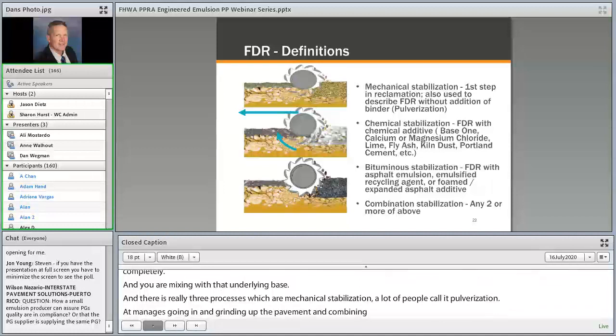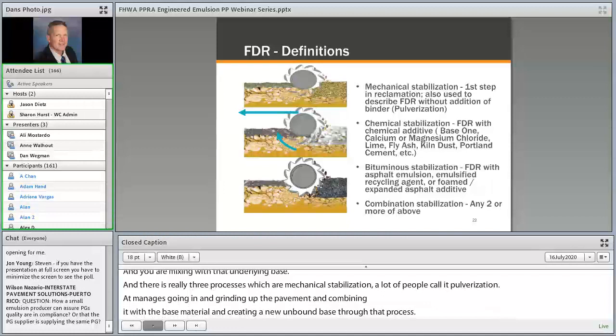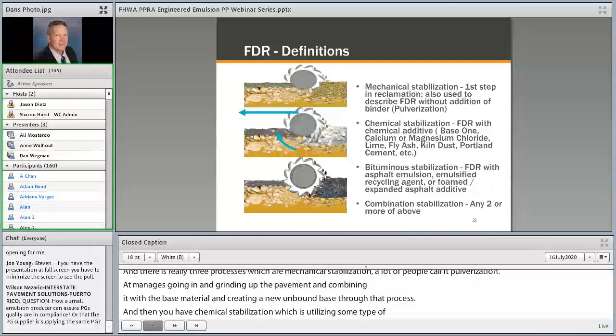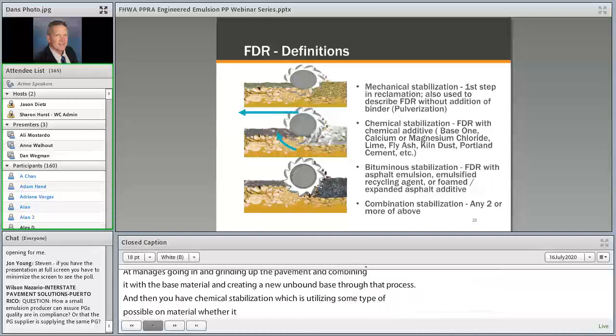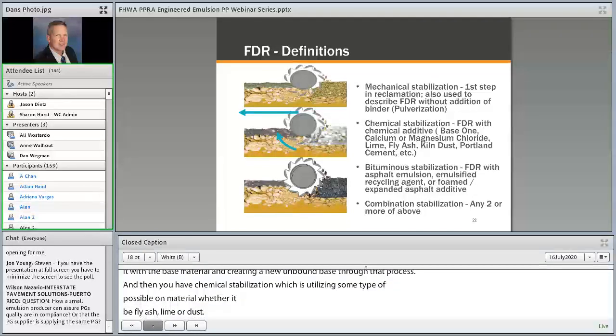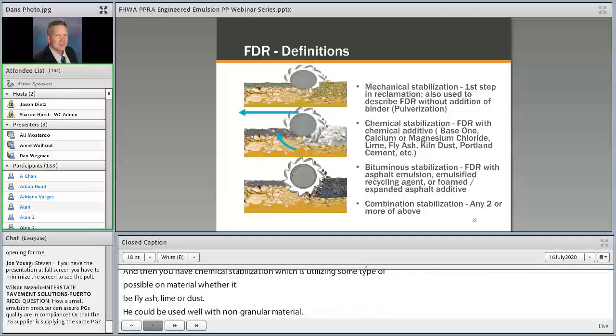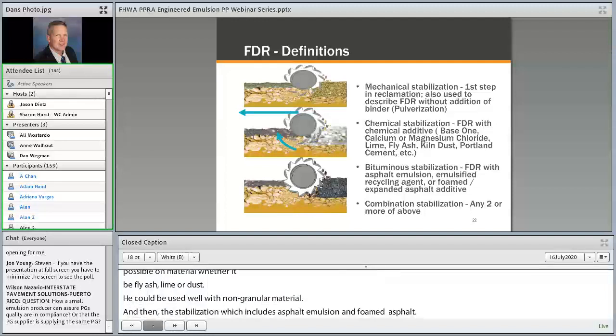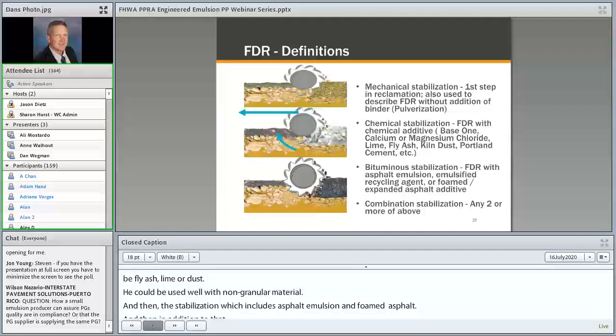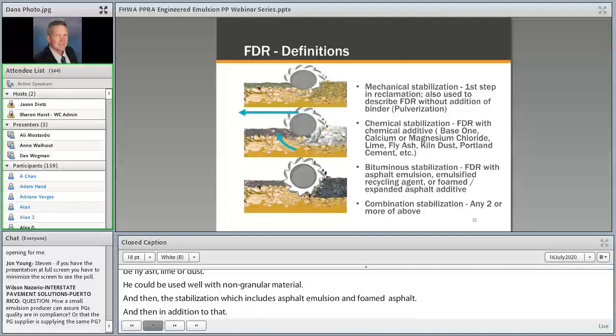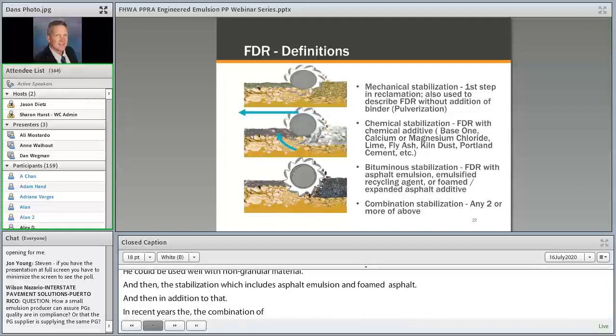And then you've got chemical stabilization, which is utilizing some type of pozzolanic material, whether it be fly ash or cement or lime, and that typically works really well with bases that have been contaminated with clay particles, organics, or non-granular material. And then bituminous stabilization, which would include both asphalt emulsion and foamed asphalt. And then in addition to that, in recent years, the combination of two or more, usually maybe a combination of two of these, would result in a process where you would use a bituminous stabilization in combination with a little bit of cement, or more like a belt and suspenders approach to an overall stabilized material.